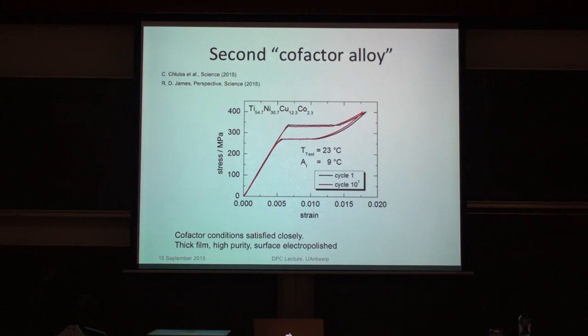So you really can contrast that with the behavior of tin at the beginning of the lecture. And not only that, look at the peak stress here: it is 400 megapascals. That's a lot of stress. You know, that's the typical yield stress in the steel that holds up this building. So it's really a lot of stress each cycle, and it's in tension. So that's homogeneous tension. That's really quite a spectacular result, in my view.